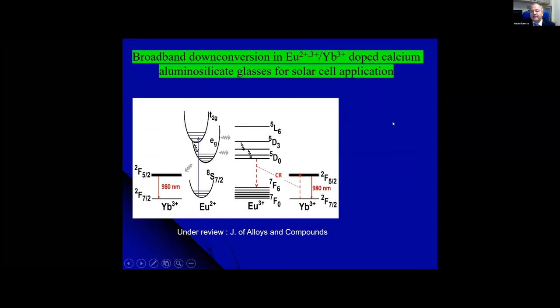And finally, the system, this paper is still under review, so I'm not going to show the details of the result, but we are combining here europium 2+ and 3+ with ytterbium, because europium 2+ has a very strong absorption coefficient in the visible. So if you can make the downconversion process with ytterbium, we have an efficient system to absorb the visible and then to transfer to the infrared.